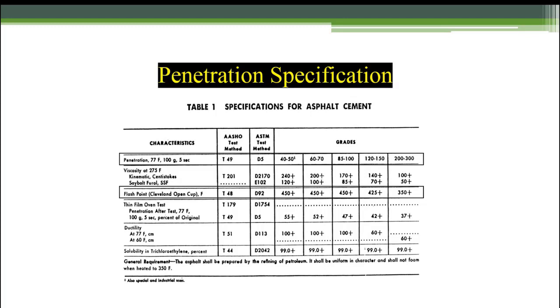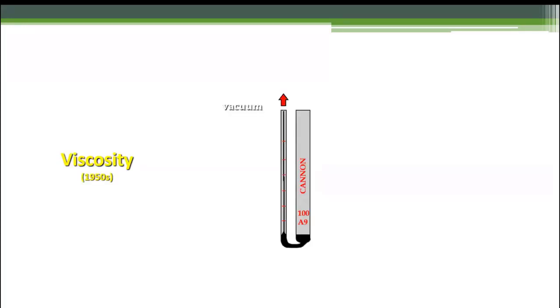The problem, of course, one of the problems with penetration graded is, how often are we at 77 degrees exactly in the Dakotas when we're constructing or mixing asphalt? Not very often, so they went to a viscosity graded system, and this was in the 1950s. Viscosity is the resistance of a material or a liquid to flow. So essentially it's a tube. In the case of straight viscosity versus under some type of vacuum, you put an amount of asphalt into the tube and measure its flow from the marks there on the capillary tube on the left side and see how far it flows in a certain amount of time.